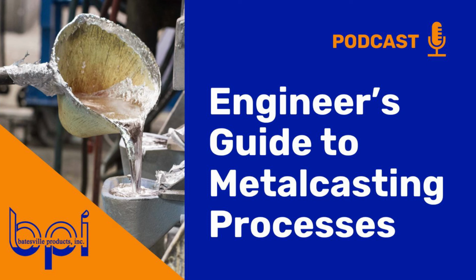Really understanding the tool itself. There's different processes in the industry, and the way the parts are casted. Different casting industries set up their molds and their presses in different ways. So really understanding the types of coating applications. If you're in permanent mold process, there's different coatings that do different things that are sprayed on the molds. Anything from cooling certain features or areas to help air get out, but to really help make a good casting. So understanding what those are up front. And on the production floor, the foundry has to be able to get those coatings into the mold. Correct. So if they can't spray that coating down in that really deep crevice, the tool is going to wear prematurely.